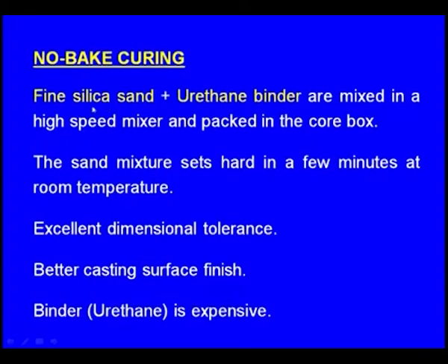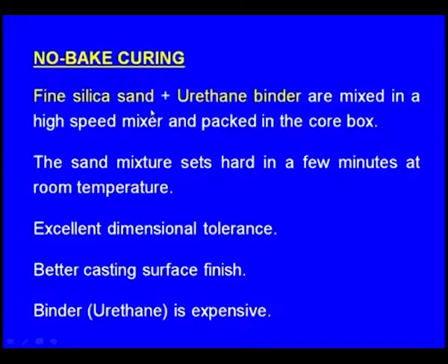Next one, let us see the no bake cured cores. What is the procedure for making no bake cured cores? Fine silica sand and urethane binder are mixed in a high speed mixer and packed in the core box. These ingredients should be mixed in a high speed mixer, and they should not be exposed to the atmosphere, because once they are exposed to the atmosphere, they will be hardened very rapidly.